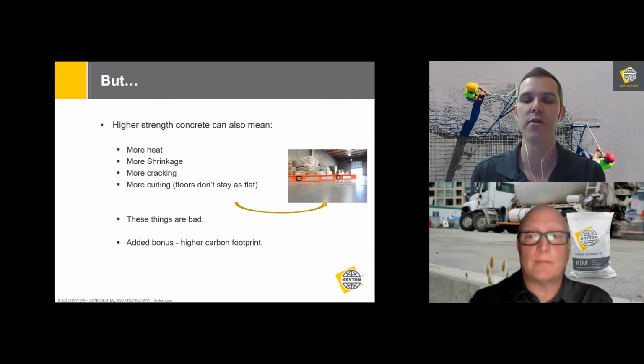The higher paste mixes generate more heat. Heat produces more shrinkage. Shrinkage produces more cracking. And if you're building a warehouse floor, when they start to dry out, they tend to curl up at the edges. So your floors don't stay as flat, which is a significant problem because one of the primary things we expect from our floors is they stay nice and flat so our equipment can move efficiently over top of them. So all of these things are actually really bad. They directly go against what you're trying to accomplish in your project. And as another consequence, using that higher strength concrete and using more cement and cementing materials increases the carbon footprint, the environmental cost of that concrete slab, which also works against what a lot of people are trying to accomplish on their projects today.